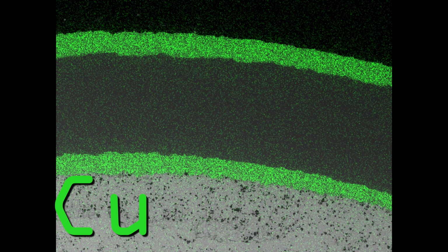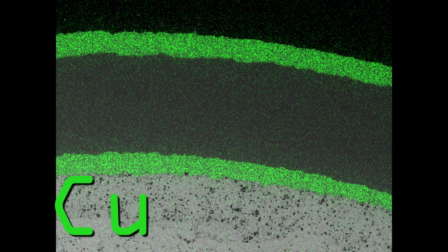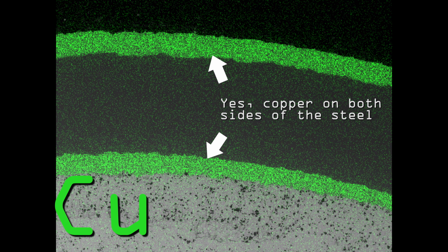Now, there are two interesting things about this bimetal jacket. First, the copper layer actually has about 10% zinc in it, actually making it a brass layer. Second, that brass layer over the steel is about 80 to 90 micrometers thick. That's about 3 to 4 times thicker than any of the copper layers I found on any of the modern bimetal jackets. I can only speculate if that is thick enough to keep the rifling from digging into the steel. I don't know, maybe.